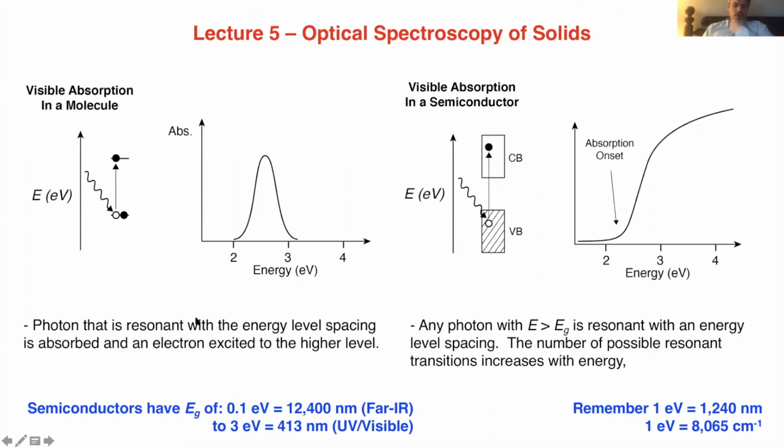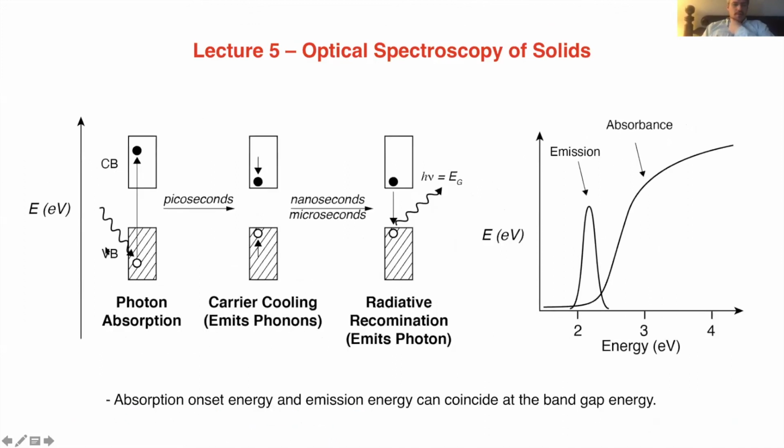All right, the other thing that happens when you photoexcite a semiconductor is that you promote an electron, and in a few picoseconds, those electrons tend to relax back down to the lowest level by jumping from level to level in the solid. The same thing happens to the hole that you create on promoting an electron out of the valence band. The hole that's left behind bubbles up to the edge of the valence band. And this process emits vibrational energy packets, or phonons, in the crystal to cool those charges down. That happens fast, on a picosecond time scale.